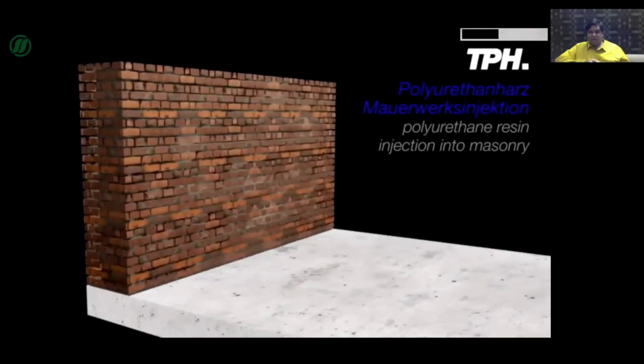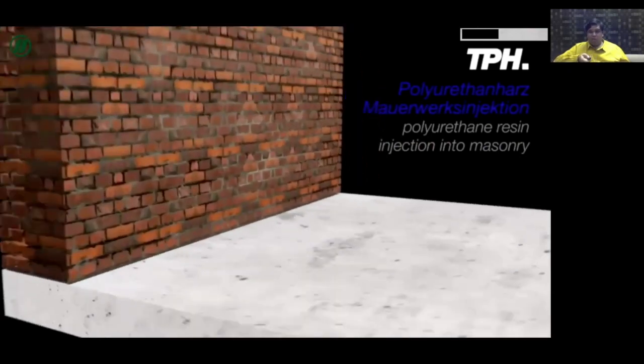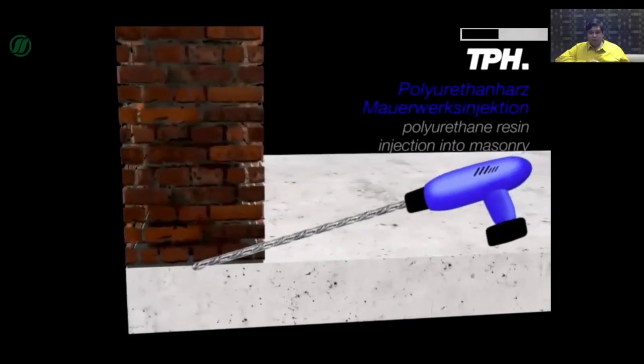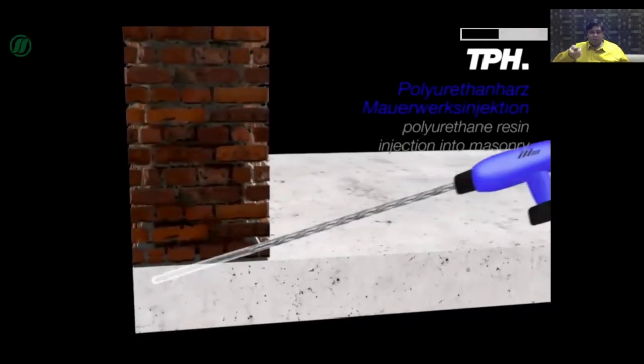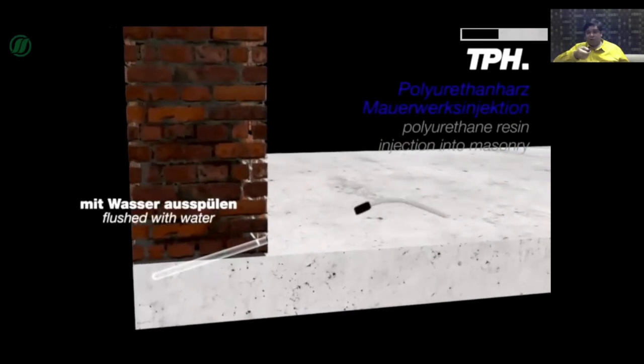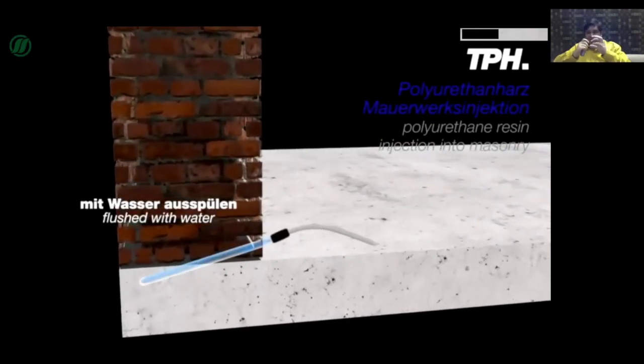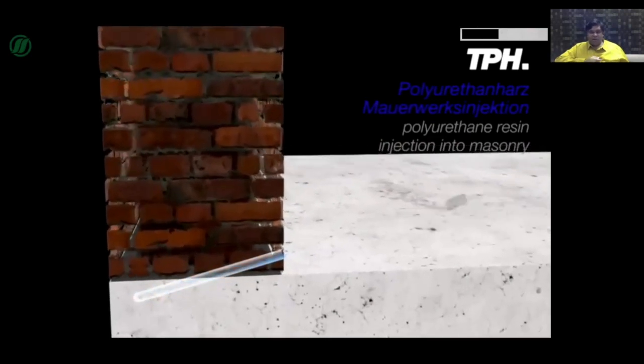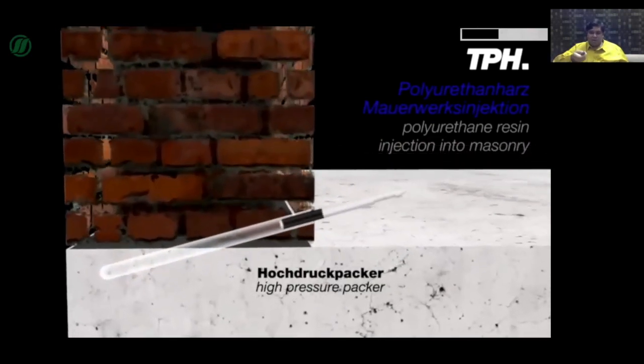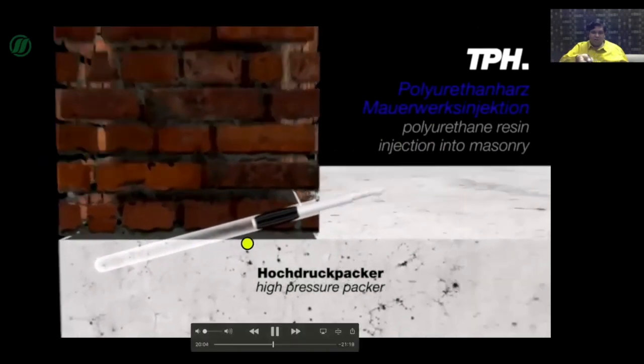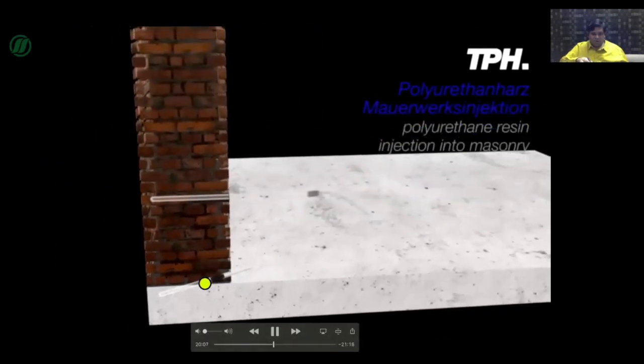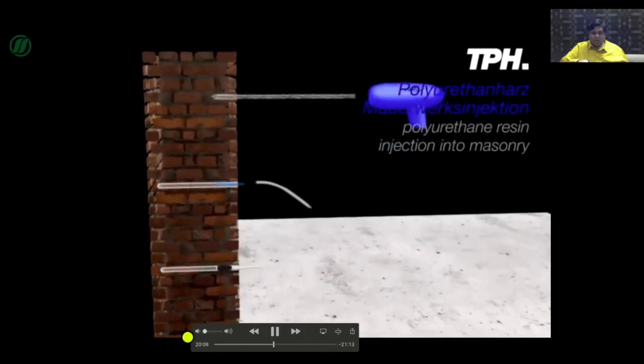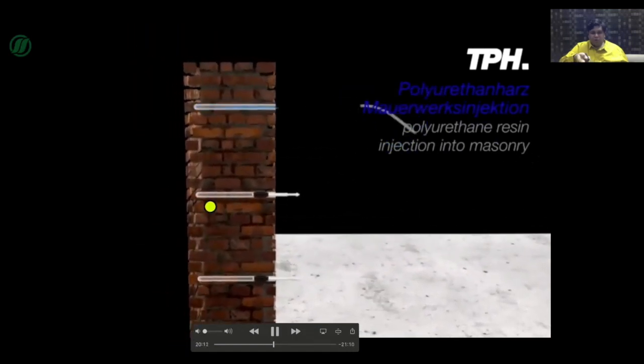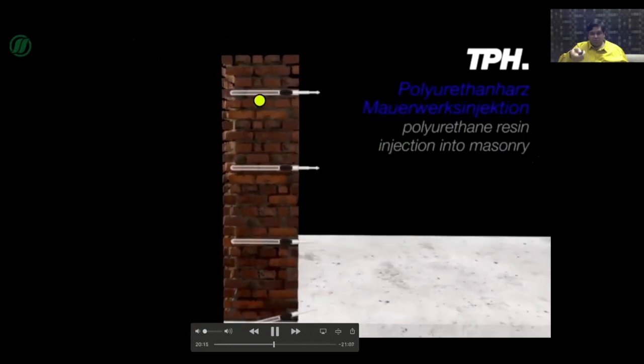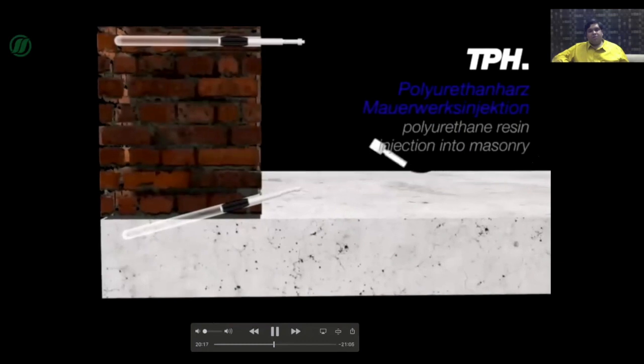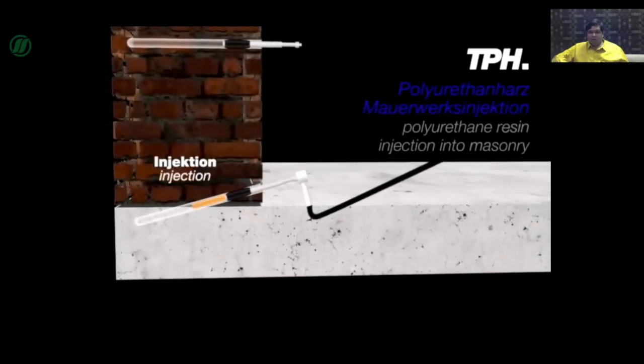Another area is injection repair or waterproofing of even things like masonry. You can do this both with polyurethane based materials, or if you want to treat more of the cracks, you can do it with flexible methacrylate gels. But the application procedure more or less remains the same. So you go along the base, you inject, you intersect both the concrete as well as the joint, and you can go through both the joints as well as through the body of the masonry wall. And you simply go in with an injection system.